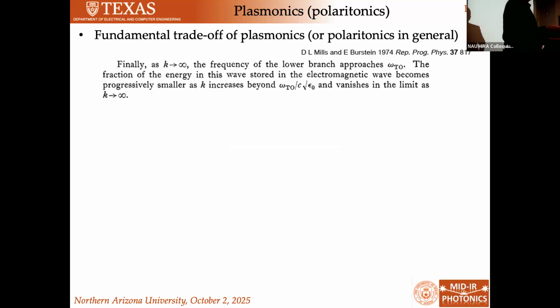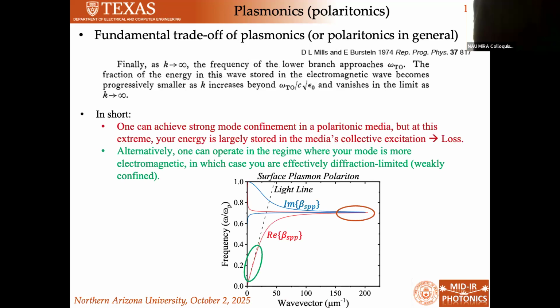So if we think about this, the reason we can condense these waves down to sub-wavelength scale is because the matter waves are much smaller. They're what gives us the size compression. And as we transfer more and more energy into those matter waves, yes, our k gets larger and our wavelength gets smaller, but now we dissipate that energy by shaking charge around. And so at some point, you're just limited. Losses prevent you from confining your wavelength down to these really small scales.